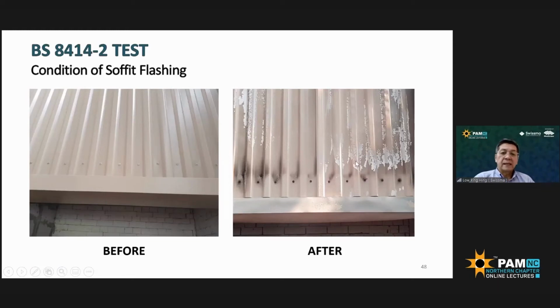So meaning to say, this trapezoidal coated steel cladding system, our Sanko Speedec in Colorbond, even at 0.42 mm BMT thickness, could withstand the BS8414 test without any problem at all. In fact, even the physical damage of the product is very, very limited, right? You can see it's only some paint burned off and blistering of the paint. And in some areas, because of the intensity, some of the flashings could get distorted, and that's about it.